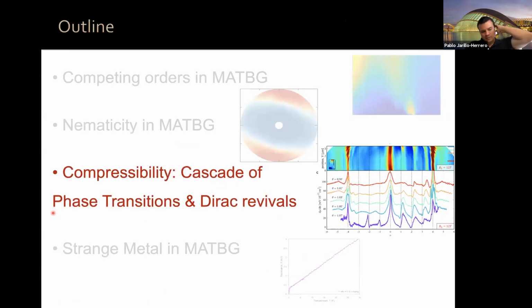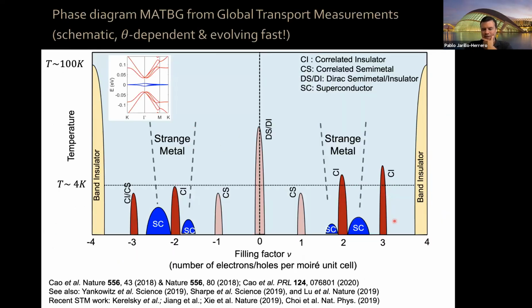Okay, so let me tell you now about our thermodynamic measurements. And I'm only going to tell you a little bit because I want to have some time to go into strange metal behavior. So this is the phase diagram, a different version, but very similar to what I showed earlier. The phase diagram for magic angle twisted bilayer graphene. Temperature here on this axis, filling factor, band insulator at 4 electrons and 4 holes per moiré unit cell when your chemical potential is in these single particle gaps.